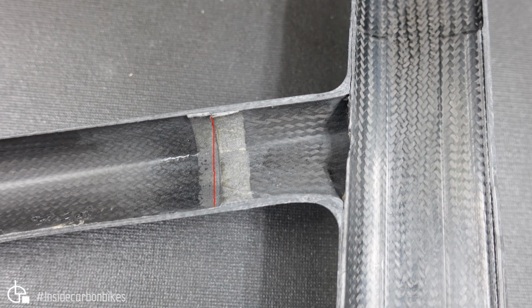Now, it is typically better to stagger thickness changes. Like on a metal tube, you wouldn't have a hard step. You'd have a gradual taper, and ideally with composites, you want each step to be the thickness of the ply. That's the minimum that you can do. So I'm not sure what the material thickness is in this case, whether it's just one additional ply and it's quite a heavy ply, or multiple plies. You'd need to do some further analysis on the layup to determine that.